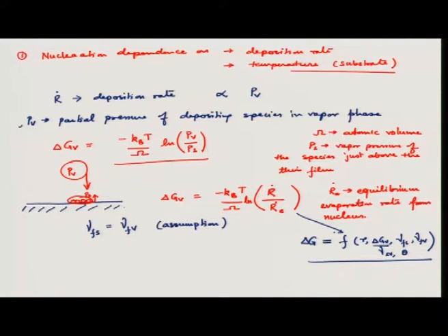And now we also know, and we can calculate from thermodynamics, that d delta G over dr should be equal to 0, and then r would be r critical, right. So, we can calculate r critical in terms of delta G_V. Now, what we want to discuss here is how this r star depends on temperature, okay.